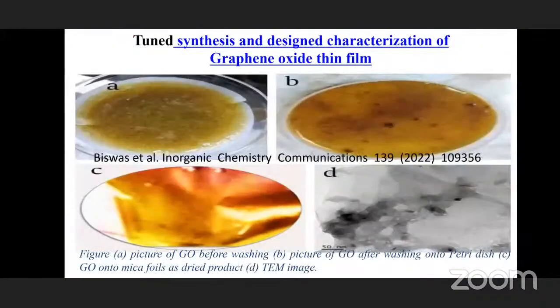We have synthesized graphene oxide, and this is a tunable synthesis. We can tune it and form a nanosheet also. Naturally, graphene oxide is a powder type oxide, but here we have synthesized a sheet type of graphene oxide. Initially it is formed by the Hummers method, but we enhanced the method using ethanol solvent.